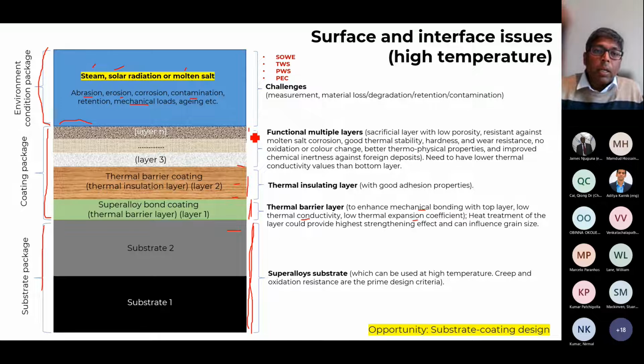So you have to think about a layer on top. I've called it functional multiple layers, and you can have certain properties so that you have a longevity or sustainable surface. It can be a sacrificial layer with low porosity and resistance against molten salt, good thermal stability, high hardness, low wear, meaning it should be wear resistant, and no oxidation or change in color, better thermophysical properties, and so on. There are so many in the list. So selection of material for the top is not easy. But there is literature which can help us come up with a better material, which otherwise has not been considered yet for this electrolyzer application.